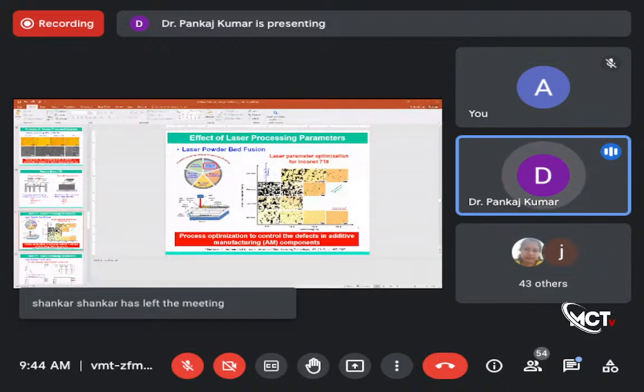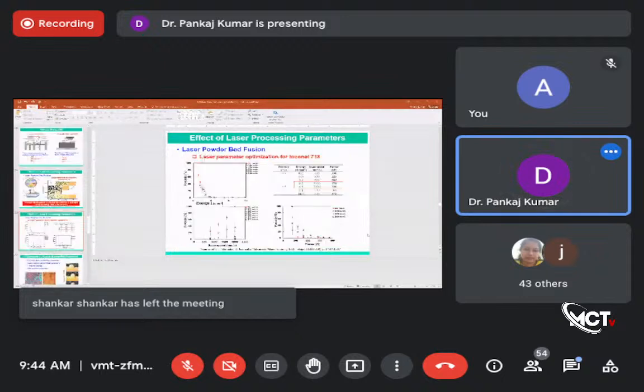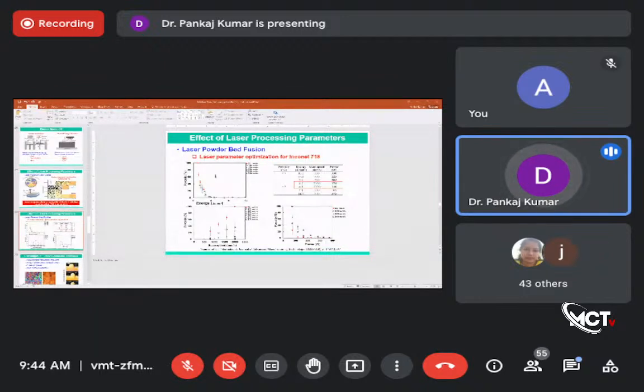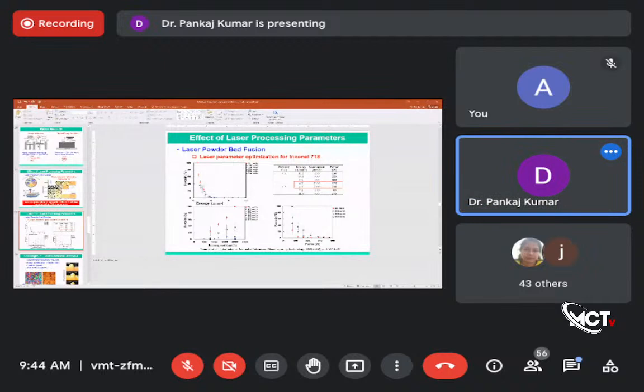Okay, so this is how it affects, right? How do the laser parameters change things? That's how it works, right? So let's look at an example of the porosity, and how it changes with energy. Okay, so you can see the porosity and energy relations. And if you look at it, a slight increase in energy significantly decreases the porosity level in the samples. That is a very important observation, right? The drastic decrease in the porosity with the energy. So this is important, right?